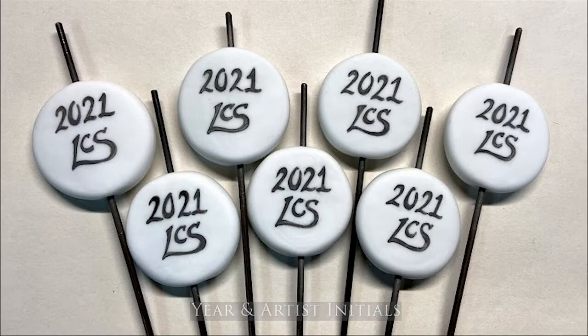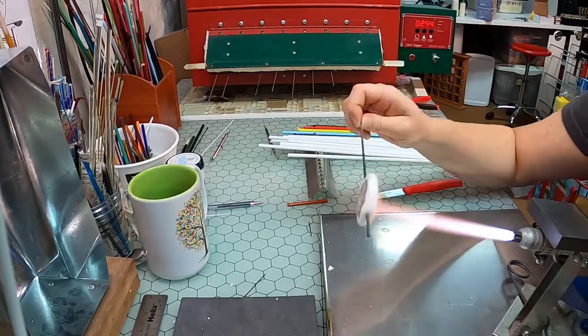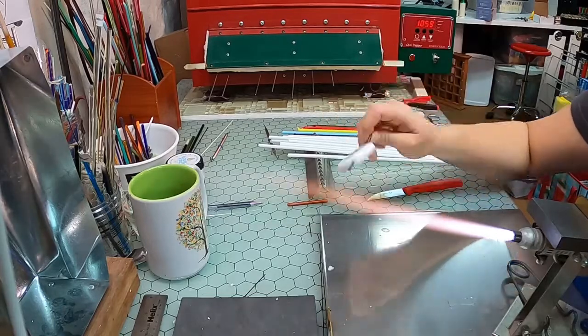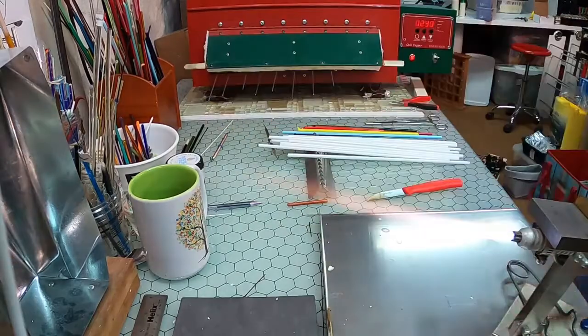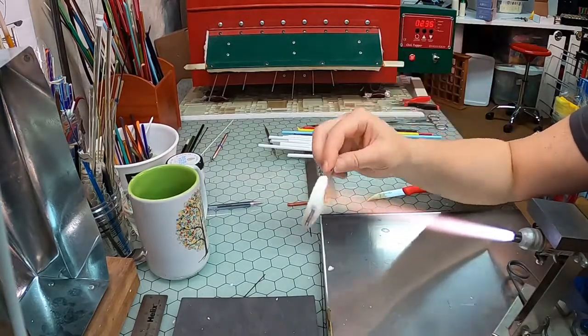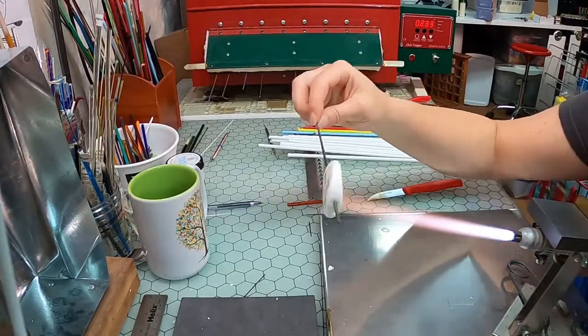A little flip reveal and these beads are ready to head back to the kiln. Heat setting the paint. Glass line paints heat set to permanence at between 1400 and 1500 degrees. Normally I would do this on flat glass in a fusing kiln, but with the rounded nature of the beads and the soft melting point of 104 glass, I have to be a bit more creative. I place all my finished painted beads in my little chili pepper kiln, using a steel rod rest to suspend the beads off the surface of the kiln, and bring them up to a little over 1000 degrees. After a half hour heat soak, I can remove each one carefully from the kiln and gently fire polish the paint until it's fully set.